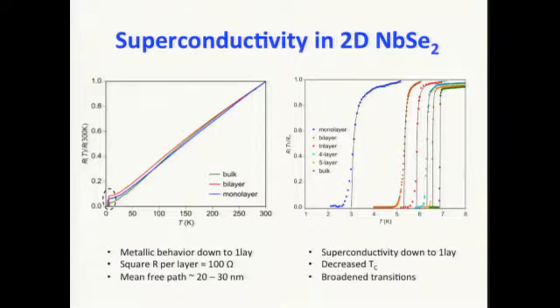If we zoom in this region here, you can see superconductivity basically remains from the bulk material down to the monolayer material. The TC is somewhat reduced from 7 Kelvin in the bulk down to about 3 Kelvin. And the transition is also somewhat broadened. We think it's probably related to the BKT transition, but we cannot completely exclude the effect of disorder on this material or inhomogeneous broadening of the transition.